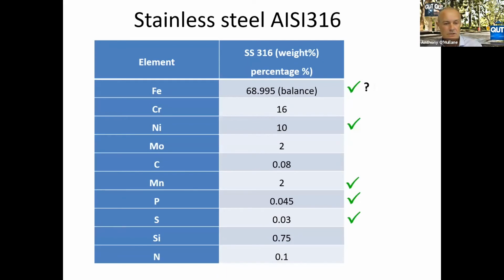So if you look at the composition of steel, obviously iron makes up most of the material. But if we look in here, again, we have our nickel, which is an active catalyst, as I said, for oxygen evolution and hydrogen evolution. We also have manganese, as we saw in the first few slides, that is also active. And we have phosphorus and sulfur, which we know, if we have it as the phosphide or sulfide, is active for the hydrogen evolution reaction. And we also have some chromium in here.